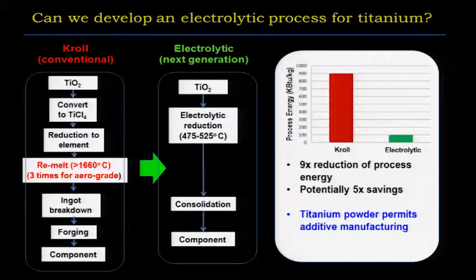titanium? There's a DARPA project investing in this, and the benefits will be in terms of the primary energy use. The old Kroll method would use nine times the amount of energy, with projected savings of five times. And then the product of this would be not only a structural material, but a titanium powder that can be used in additive manufacturing.